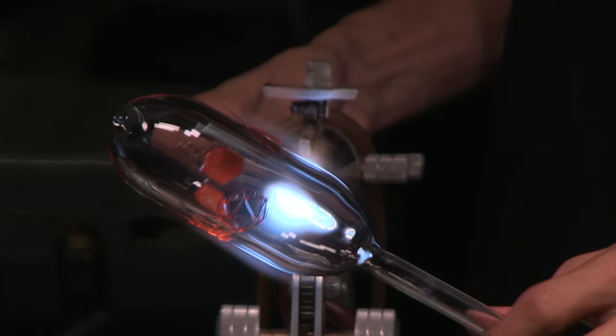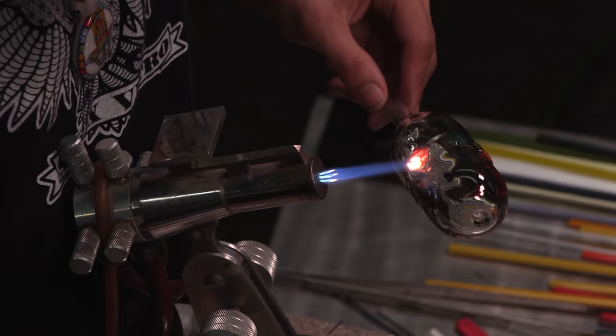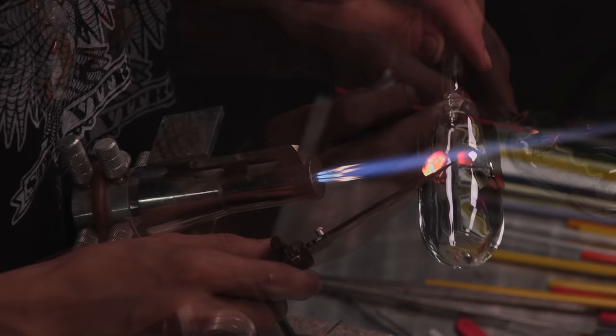And to answer your question more specifically, as far as why I was trying to get it all in one go, as opposed to doing multiple strips of lines, what I've noticed is that the more you do multiple lines next to each other, sometimes you'll get the surface of the glass you're drawing on too hot, or the colors you're working with won't work with each other very well, and you'll end up with a 3D effect when you're drawing. So let's say you're just filling in a square or a circle. You have to draw three lines next to each other.